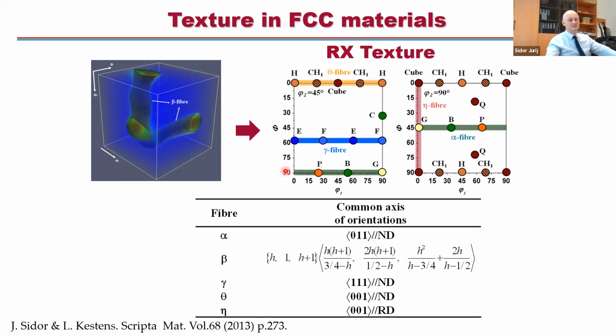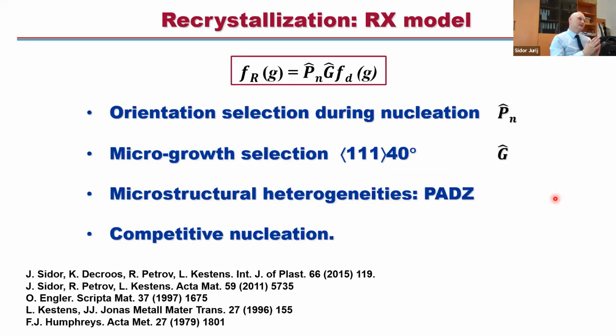You have alpha fiber components like Goss, some P component sometimes, and in some instances you also have very big gamma fiber components, but that's due to the presence of particles which you normally have in aluminum alloys. Okay, then in order to understand the evolution of crystallographic texture, we developed a model which allows us to predict the evolution of crystallographic texture during recrystallization based on the deformation texture.